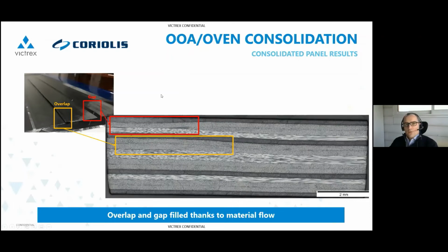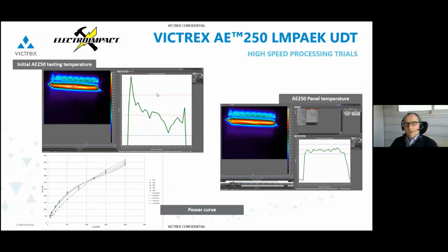So again, we also worked with Electroimpact on this topic, and obviously it's not the same machine. They adapted their equipment for this high speed. And when you're processing Victrex AE250 tape at 100 meters per minute, that requires an extensive manipulation of the laser power curve to maintain a constant temperature at the nip point through the entire course. So the material is processed with an initial add speed, accelerating up to maximum transverse speed, and then decelerating down to cut speed. When transitioning between a lower and higher speed, a third order equation became necessary, even for the flat coupons. So different curves were established for each of the first plies. That's what you have on this graph here.